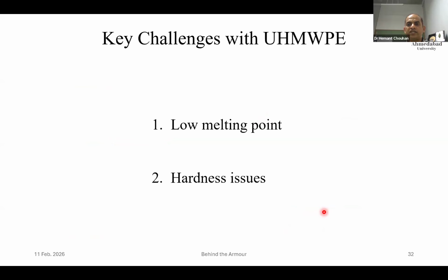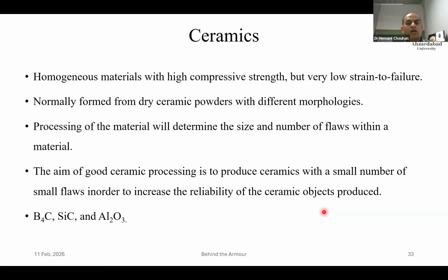Polyethylene, we all know, you can increase the molecular weight, but you can't change the melting point. And being plastic, don't expect very high hardness. Yet, multiple layers of this material can successfully defeat lead and mild steel core bullets. So that is a good feature for us. Talking of the moment we have to migrate from soft core bullets to hard bullets, that is HSC or sniper, you have no other option but to place a higher hardness material in front of this polymeric backing.